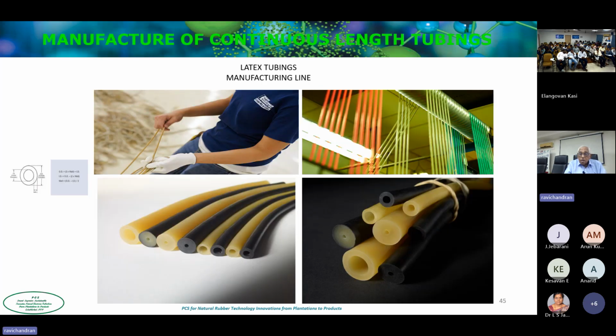This is tubing. Latex can come in tubing. Now there are some specialized manufacturers who can make latex tubing that are up to half a kilometer in length, continuous tubing. They use a wire mold, and as you can see, it goes below this. There is a latex tank, and the wire goes multiple times through this latex bath and builds up the thickness, and then it goes into a drying oven where it is dried, and then finally there's a mechanism for yanking out the cord, the wire, from the center of it.